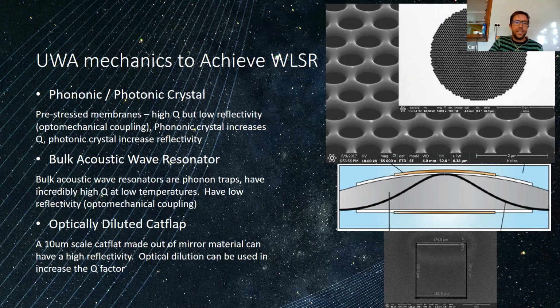The second device we're investigating is called a bulk acoustic wave resonator, and this is a beautiful piece of quartz that also acts like a phonon trap. That's the middle figure. These devices have been used in the telecommunications industry, but work by Mike Tobar's group has shown that they also have incredibly high Q factors at low temperatures. The only issue with them is that they have very low reflectivity because it's just a piece of quartz, with no coatings on it, and it's hard to get large optomechanical coupling.